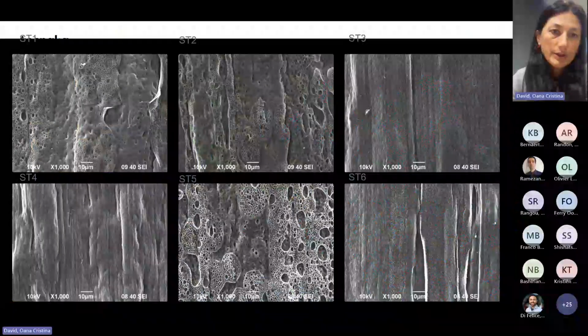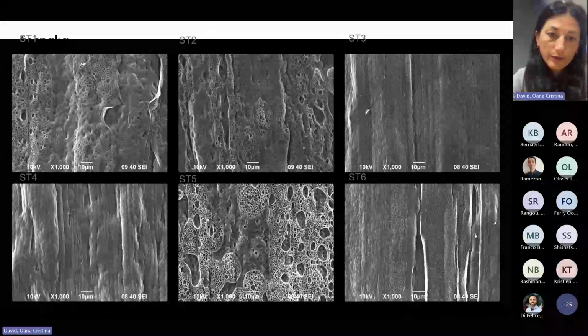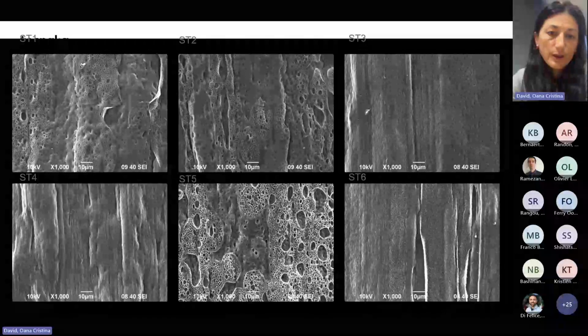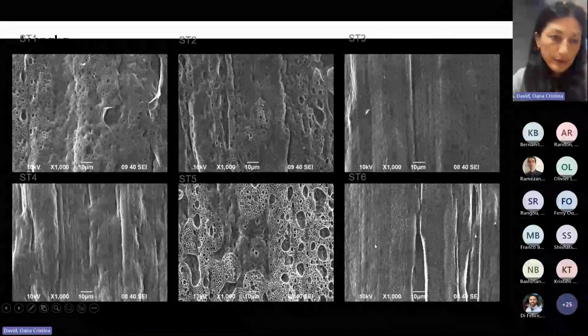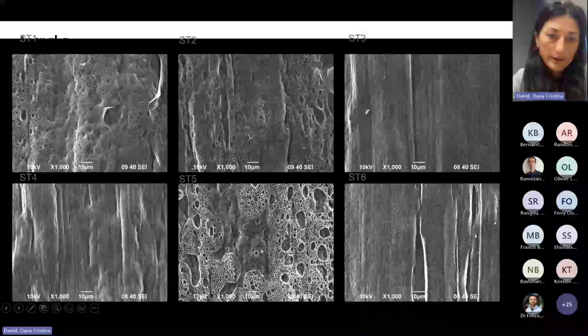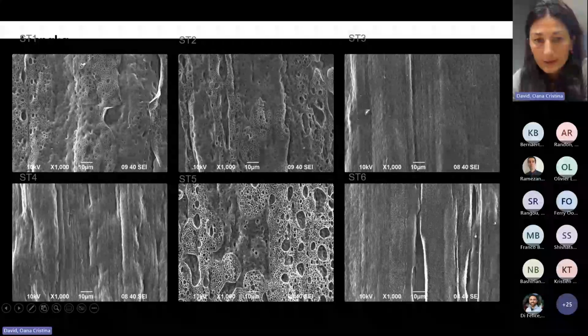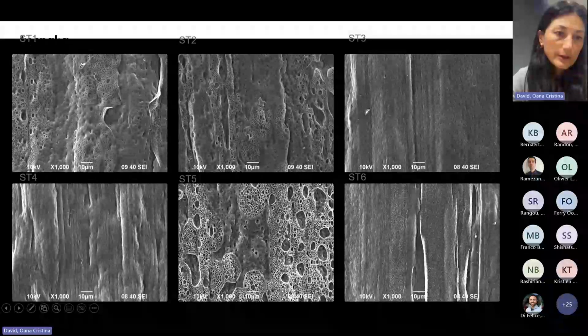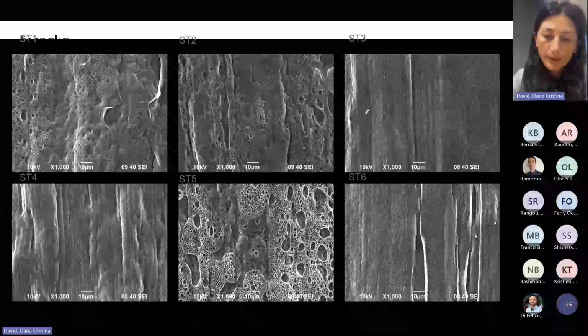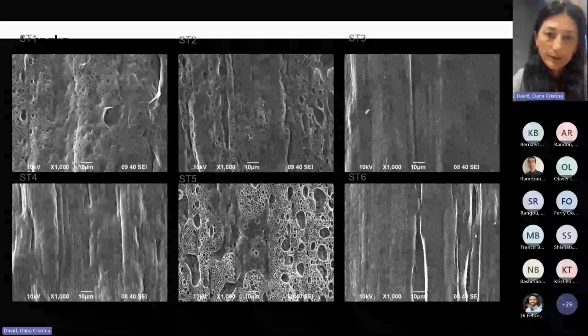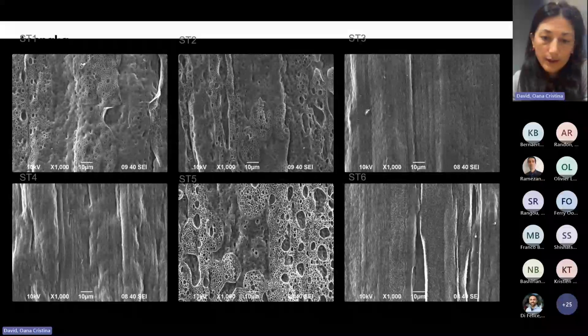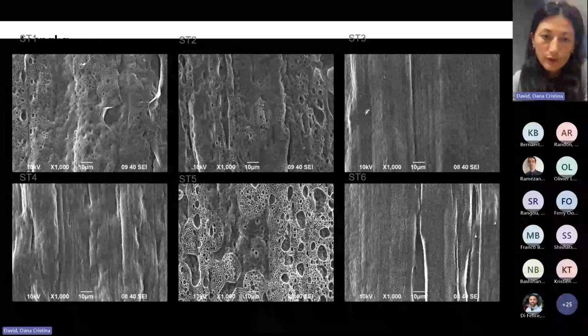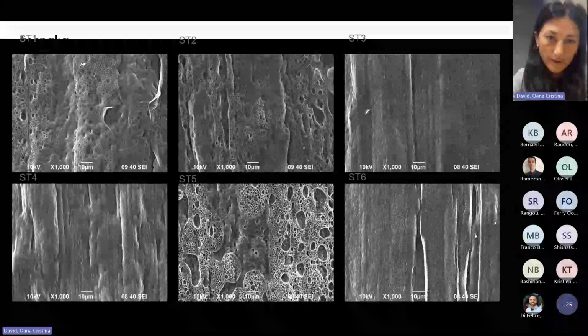If we look at the outer surface, here we would like to have a porous outer surface, and we still have to improve that. But it's very difficult based on images to compare the fibers between them, and making this kind of image evaluation to check the porosity is also difficult here.